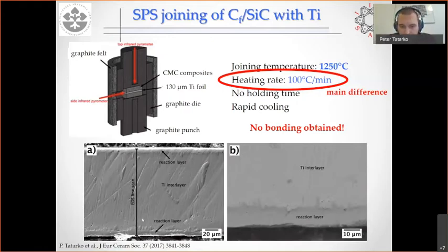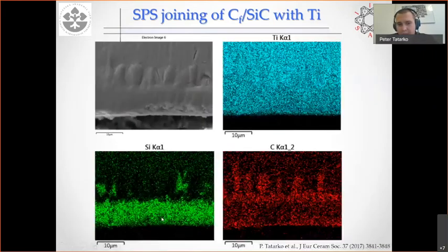But we still could polish it. The polishing is not perfect, but doesn't matter. It shows what I want to see. What I want to show you is here the reaction layer. If we did, of course, EDX, you can see this is titanium, and here you see silicon and carbon. So also by XRD and also EDX mapping on TEM, we confirmed that there was a titanium carbide forming and